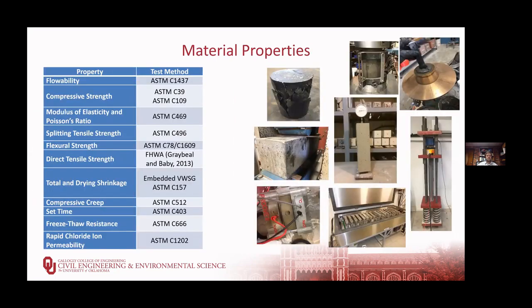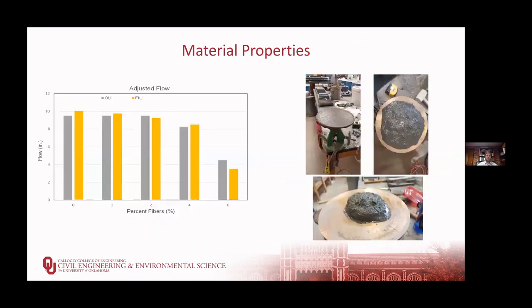So once we had the mix design developed, we extensively examined the material properties, including flowability as a fresh property, compressive strength, modulus of elasticity, splitting tensile strength, flexural strength, direct tension, shrinkage, creep, set time, and then for durability, we looked at freeze thaw resistance, rapid chloride ion permeability, and we did some corrosion testing. So, just going through a few of the different properties of this mix design.